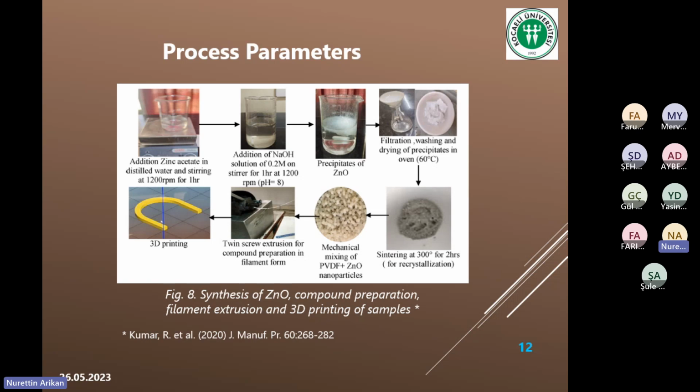It's possible to increase the piezoelectric behavior of PVDF either by poling, as we already experienced, or by particle doping. And for particle doping, mostly the already piezoelectric materials, the piezo ceramics, are preferred, barium titanate or zinc titanate.